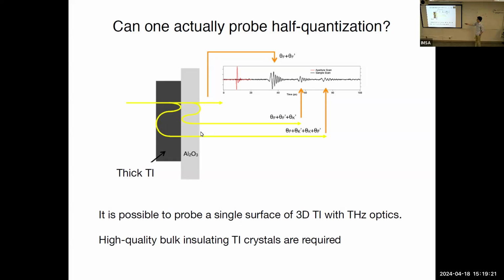But if you look at the second pulse, which goes all the way down to the surface of this dielectric, bounces back, and then goes through here, the total rotation is going to be the Faraday rotation of top plus the Faraday rotation of bottom, nothing from the dielectric because it's just a normal insulator, and then one Kerr rotation at the reflection, and then one Kerr rotation at the other reflection. So if you take these two measurements and subtract one from another, you should in principle be able to get this half quantized effect, unlike all other measurements which are just integer quantized.